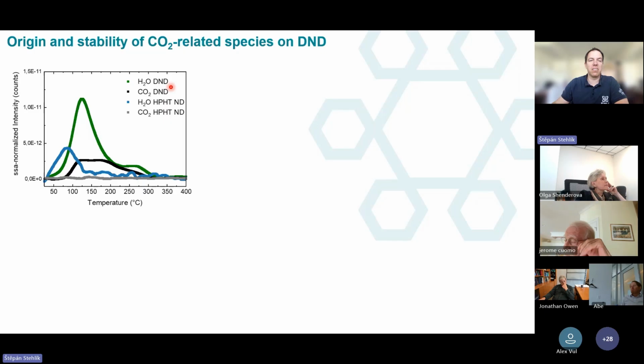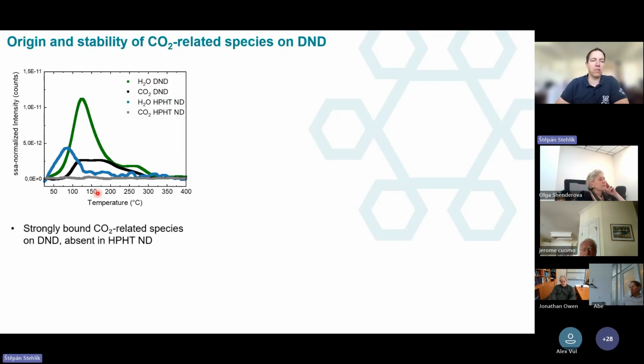So the hydrogenated DNDs are very hydrophilic, and they keep the water up to very high temperatures, actually. And also there is connected the CO2 signal, so you can see that the CO2 is dissolved in this hydration layer and goes out with this water up to 300 degrees C. In contrast, on the HPHT nanodiamond, we saw just some weakly physisorbed water, which was gone up to 120, and no CO2 signal.